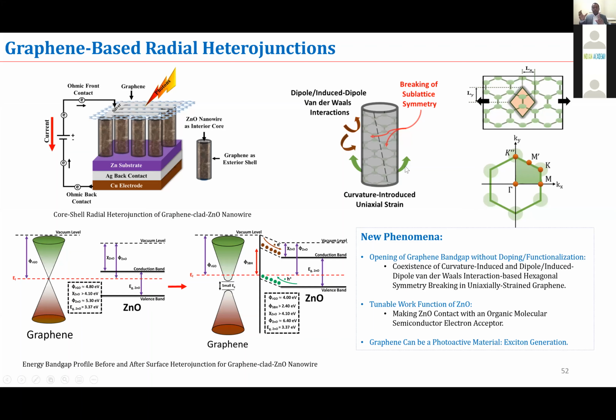And because we can wrap graphene, the symmetry is broken. And because the symmetry is broken, now we can open the band gap that we discussed in the beginning, that graphene is a zero band gap material. And this is the process where we can open the band gap as well. And that is good for light absorption, because you have a band gap, it will be able to absorb, it will be able to act as a photoactive material.